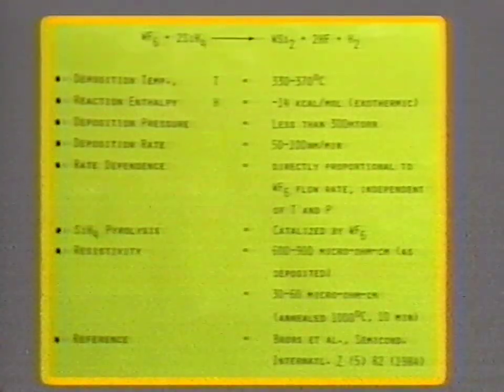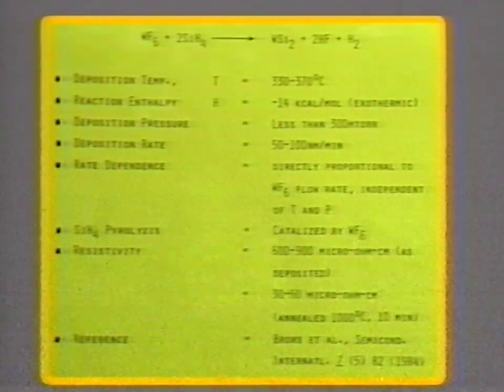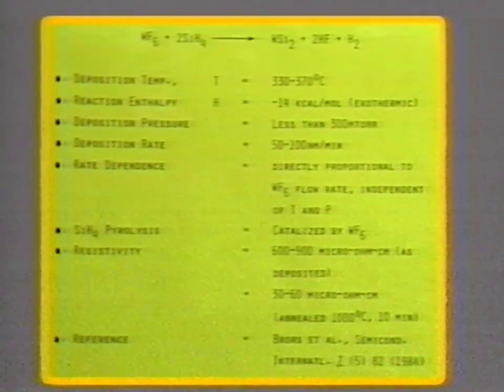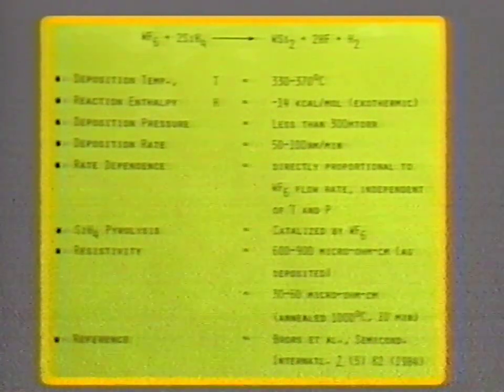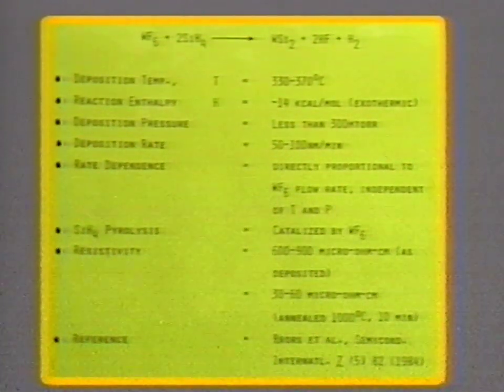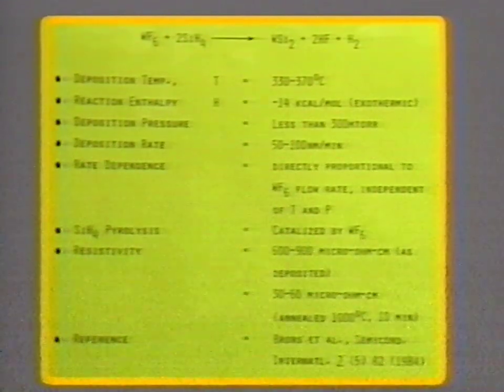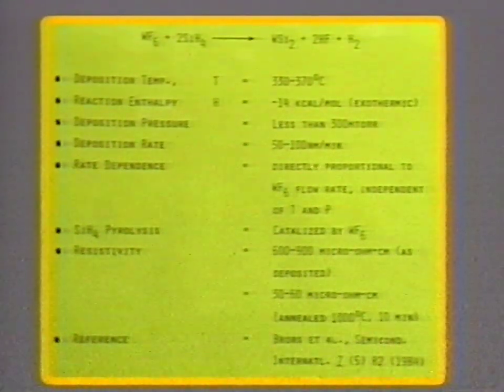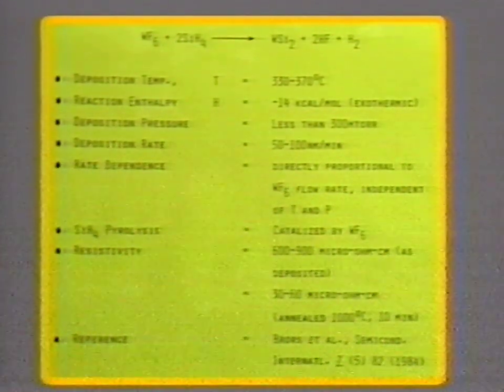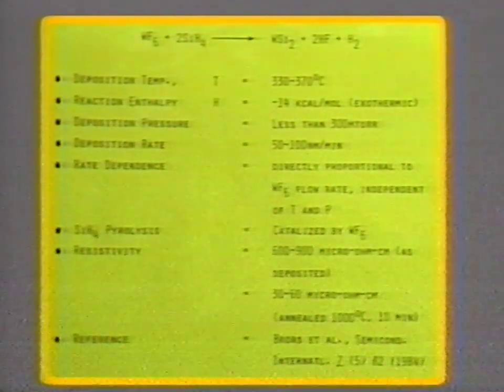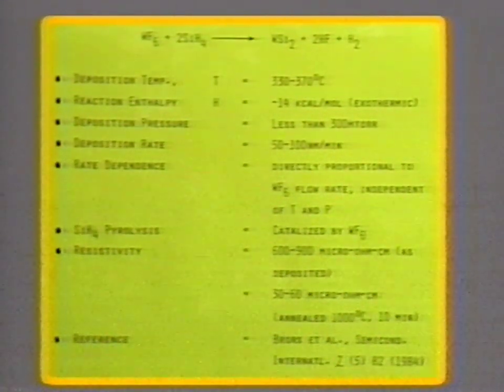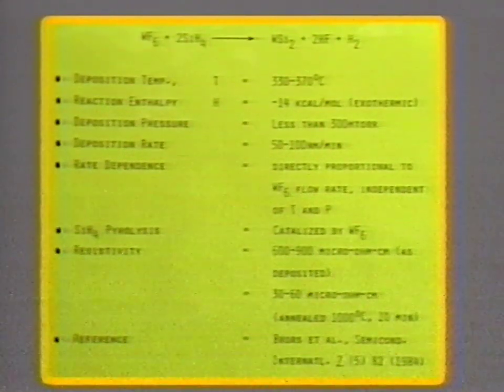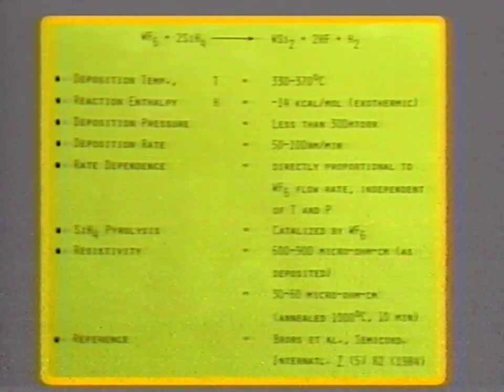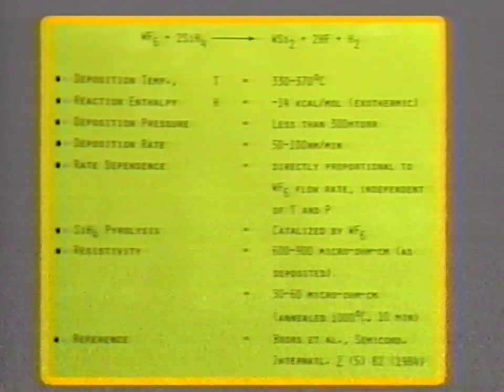Okay, now the tungsten disilicide or tungsten silicide formation is shown here. Again, we can use tungsten hexafluoride, reacting this with the silane to produce the tungsten disilicide and HF as the byproduct. In this case, the temperature of deposition is in the range of 330 to 370 degrees centigrade. Pressure is in the range of 300 millitorr or less. And deposition rates are typically 50 to 100 nanometers per minute.